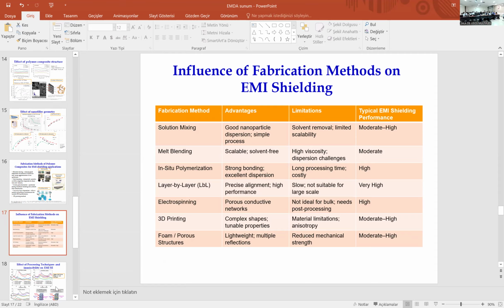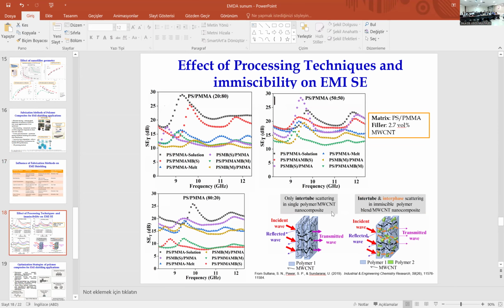Here is an example of the effect of processing technique and immiscibility of the polymers on EMI shielding performance. This figure shows the total EMI shielding of the samples prepared by different processing strategies as a function of frequency in the X-band region. Different preparation approaches and blend compositions alter the level of selective localization, nanodispersion, and phase morphology. Consequently, the EMI shielding efficiency of the blend nanocomposites varies, and the solution technique gives better EMI attenuation and better dispersion of the filler.